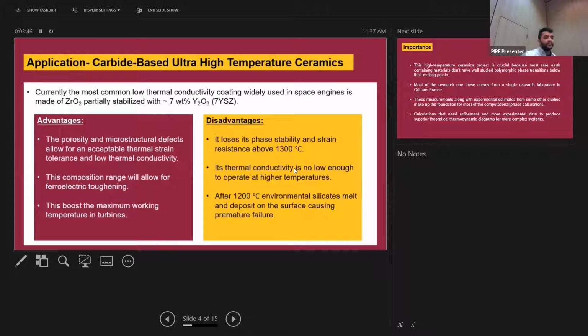But in more recent years, they've wanted to increase the operating temperature of these turbines to, I want to say, greater than 1,500 degrees Celsius, which is pretty high, right? And this material specifically loses the phase stability and strain resistance around or above 1,300 degrees C. Its thermal conductivity is not low enough for operating at these high temperatures. So that's why you have to research other materials. And after 1,200 degrees Celsius, environmental silicates melt and deposit on the surface of the coating, which might cause them to